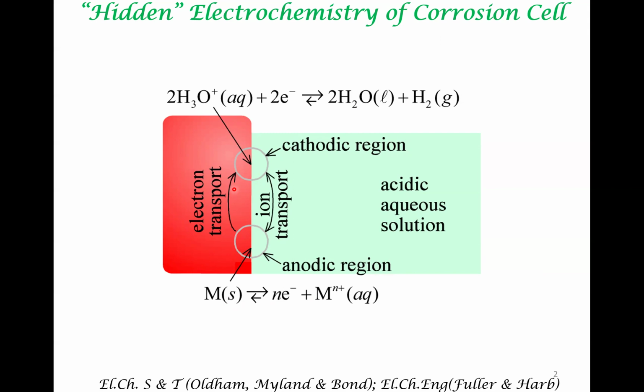What is the primary constraint? In many electrochemical systems, the electrochemical system might involve supply from an external source. But as opposed to this, the electrons that are generated from this reaction have to be consumed by this reaction. That is, when you have an oxidation reaction that generates electrons, at steady state, these electrons have to be consumed by a reduction reaction.